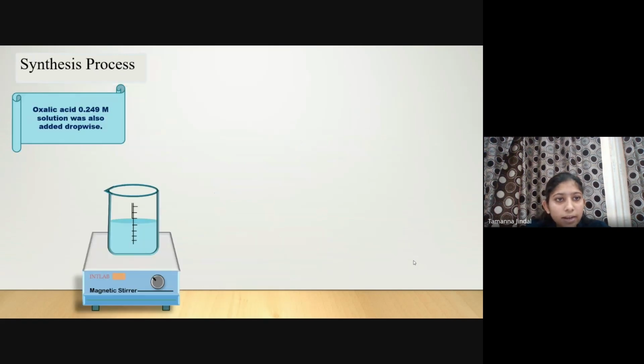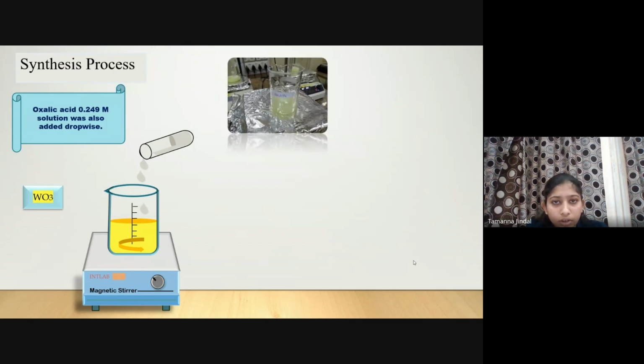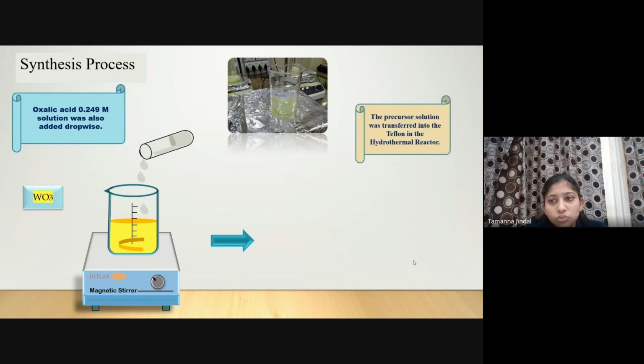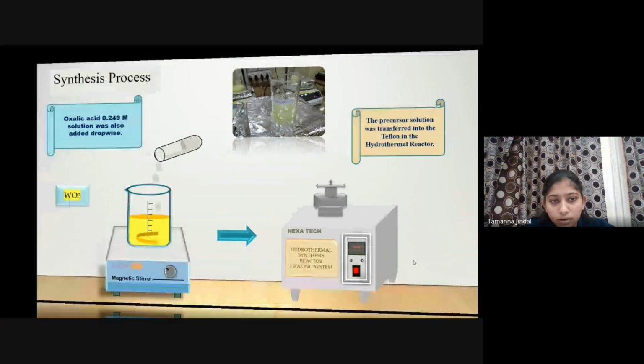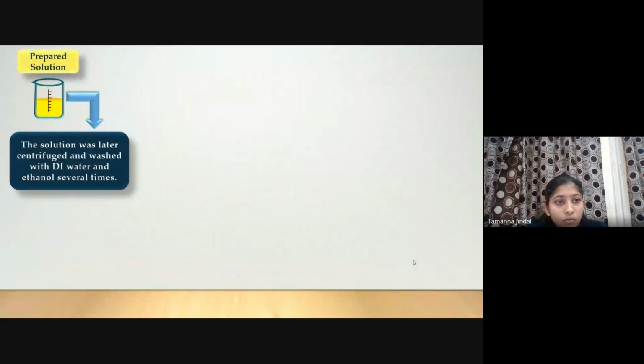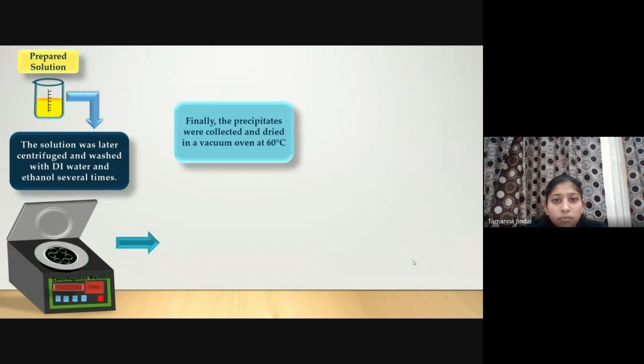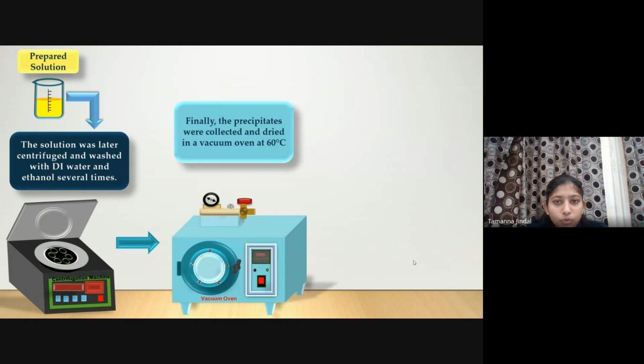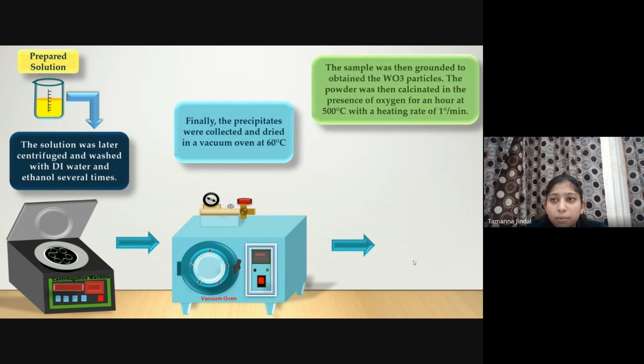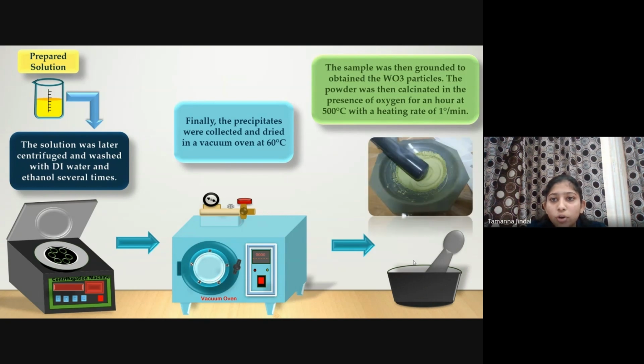After that, 0.249 molar oxalic acid solution was also added dropwise, which changes the color of the prepared solution, and we get the solution of WO3, as shown in the figure above. After that, the precursor solution was transferred into the Teflon-lined hydrothermal reactor. Finally, the prepared solution was centrifuged and washed with DI water and ethanol several times. After that, the precipitates were collected and dried in a vacuum oven at 60 degrees Celsius, and the sample was then ground to obtain the WO3 particles. The powder was then calcined in the presence of oxygen for an hour at 500 degrees Celsius with a heating rate of 1 degree per minute.